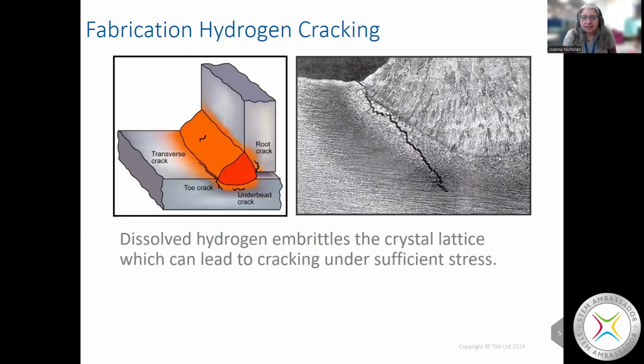Just as a quick teach-in on fabrication hydrogen cracking, and then a little bit on service cracking as well. Fabrication hydrogen cracking can occur at various different places in a weld. Could be along what we call the toes, or underneath the beads, from the root of the weld, or across the weld. And what happens is that hydrogen gets into the weld pool when it's molten and then ends up in the solid material later. The hydrogen is dissolved. It's atomic hydrogen rather than the diatomic hydrogen that we would normally expect. It's not H2, it's just H. And if we get enough of it in, then it can lead to cracking if we've got enough stress.